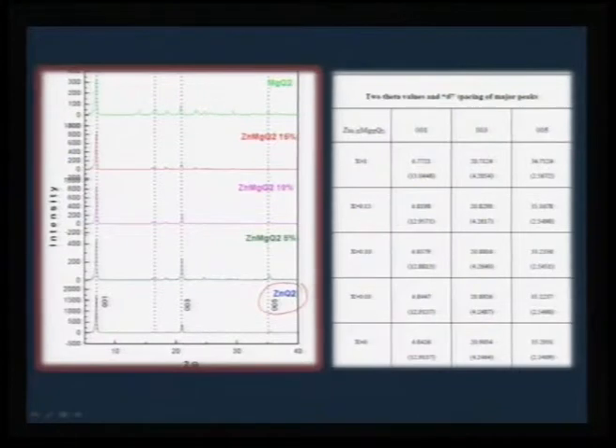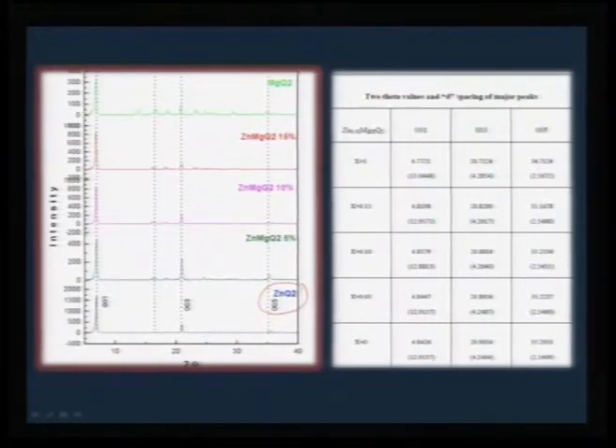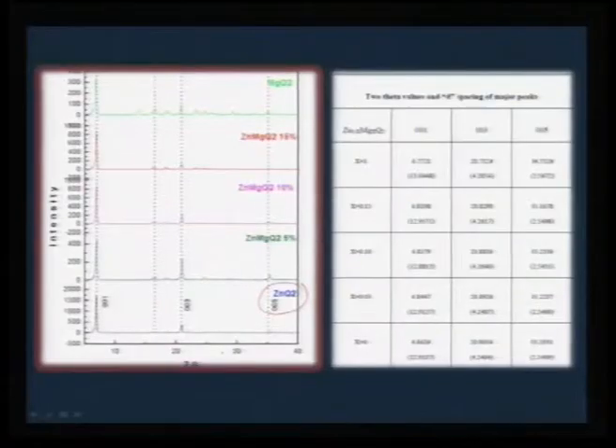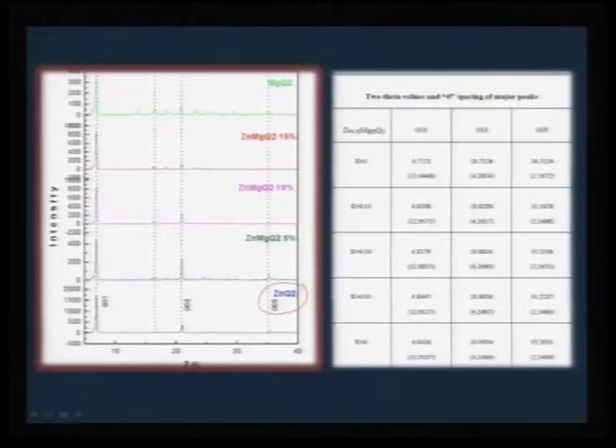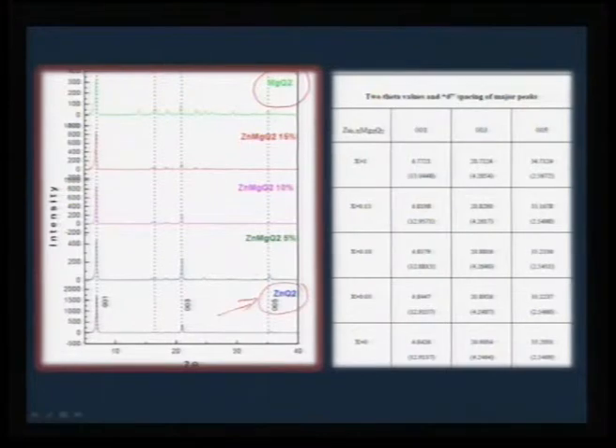Zinc quinoline (Zn-Q2) is nearly cubic in its x-ray pattern because you have only three obvious major peaks that are nearly equidistant. Just by looking at the precursor x-ray, one can guess what sort of crystal symmetry it can have. In this case, because of equidistant peaks, you can easily map it to cubic — higher symmetry gives very few peaks, whereas more complex structures give more peaks. Magnesium Q2 shows a similar pattern, which gives us the privilege to dope magnesium and zinc together.